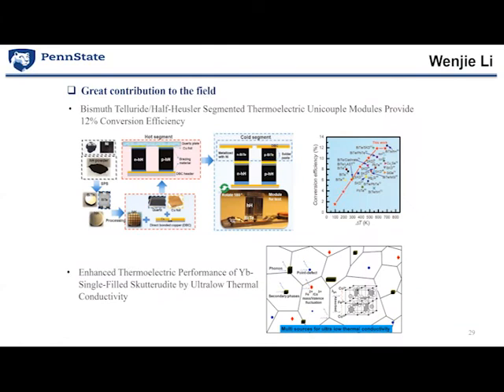He has already made great contributions to the thermoelectric field. Here are two examples. The first example is the work he did at Penn State. It is a segmented thermoelectric device with electrodes, which can be demonstrated in conjunction with heterogeneous materials integration. This is the bismuth telluride half-Heusler segmented thermoelectric module. It can generate a world record conversion efficiency of around 12% under a temperature difference of around 584 K. So based on the figure on the right-hand side, you can see this is so far the highest conversion efficiency in thermoelectric modules compared to previous works. So this will make a huge contribution to the industry application of thermoelectric materials.